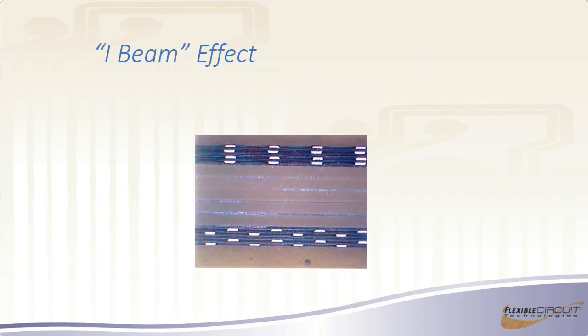This is the I-beam effect. By stacking conductors on multiple layers, you're essentially increasing the thickness, and the thicker your board is, the more tension and compression you're going to create when you form it. So we typically recommend staggering those traces like you see in the bottom there. And a lot of designers like to have their signal return paths stacked on top of each other, and that's fine, but then stagger the pairs. So these here would all be shifted in between, so they fell in the middle there. And that way you can kind of, again, the balancing act. You'll make it slightly thicker, but not so thick that you end up with mechanical problems when you bend it.